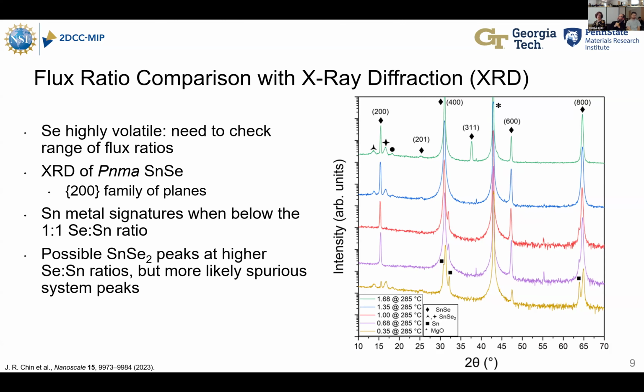Thank you. Jonathan, did you do any measurements to look for twinning in your film? I mean, X-ray phi scans or anything? Yes, we have done some in-plane XRD if that's what you're asking. But right now we're predominantly just seeing that twofold orientation with the orthorhombic tin selenide. I haven't seen any particular effects like that, but that's also not something I've particularly looked into either.